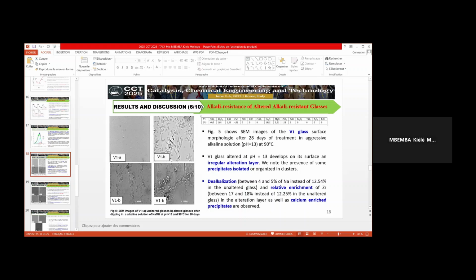because we obtain between 4 and 5% of sodium instead of 12% in the reference glass, and the relative enrichment of zirconium between 17 and 18% instead of 12.25% in the reference layer. We can also note calcium-enriched precipitate on the surface.